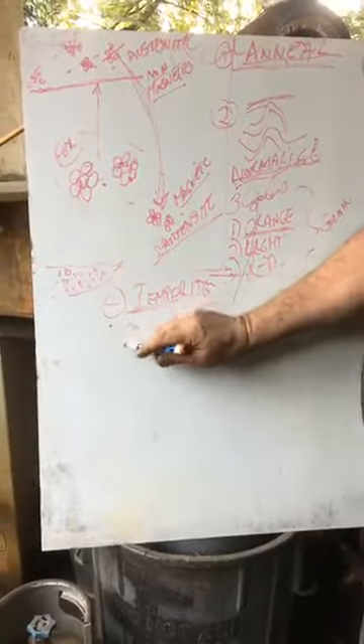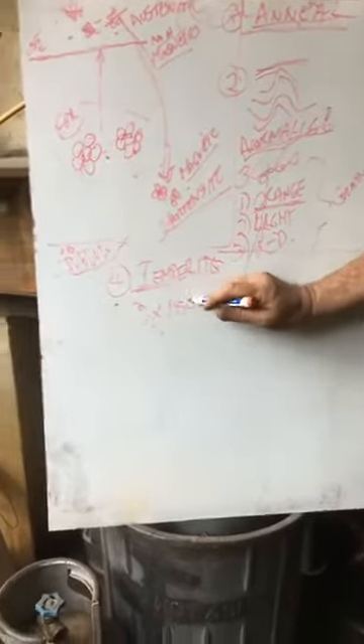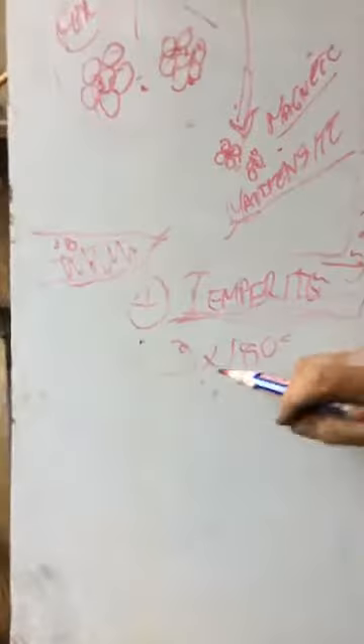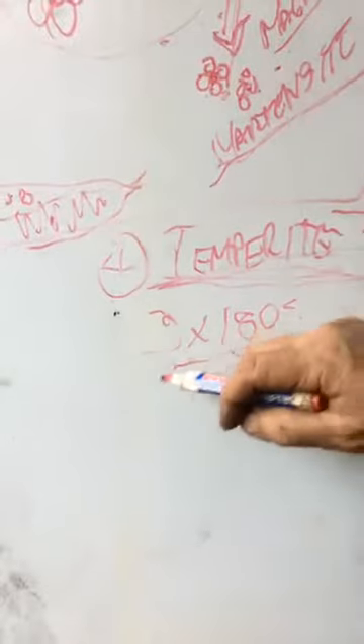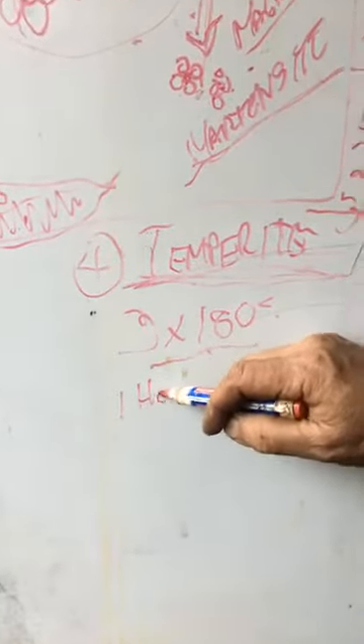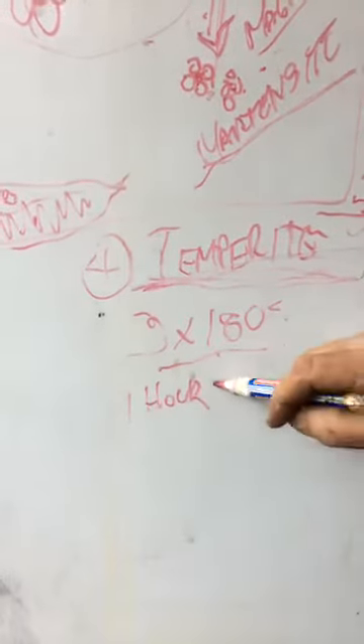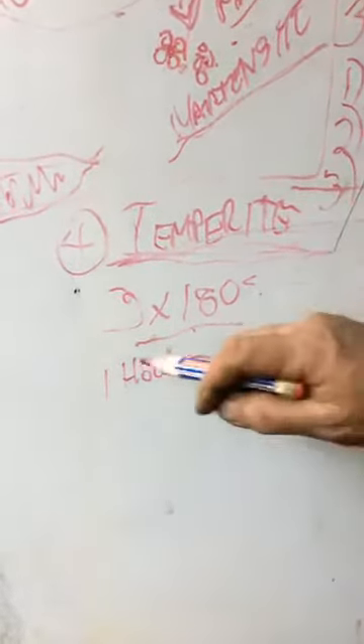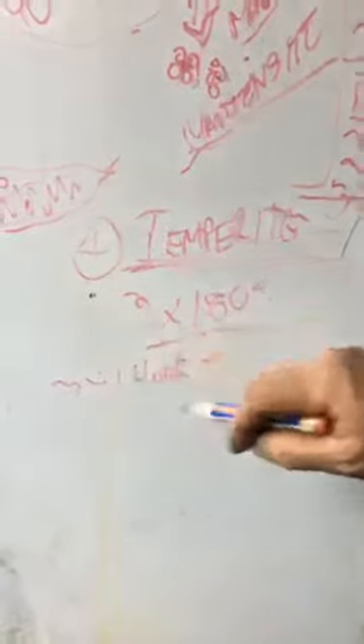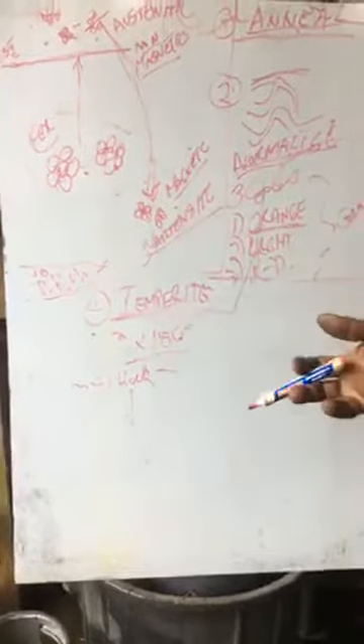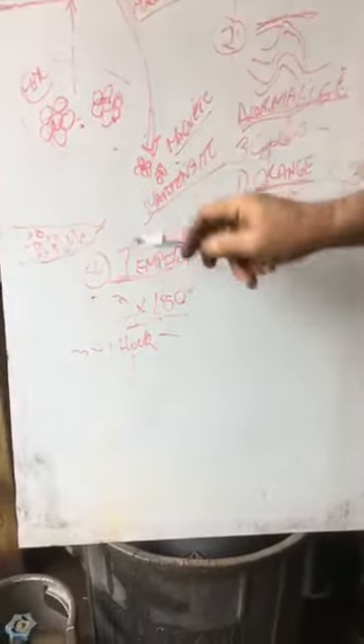I work on 3 180-degree Celsius cycles in the oven. I take it out after every hour. Then I just run it under the cold tap, cool down. So 3 1-hour cycles at 180 degrees. After that, and because this grain structure keeps on refining itself, some of them up until it's sub-zero, I put it in the deep freeze overnight. So anneal it, normalize it, harden it, temper it.